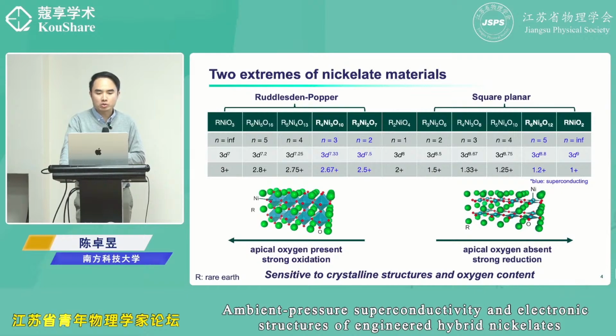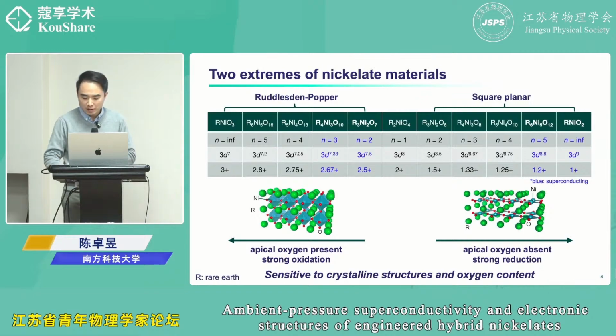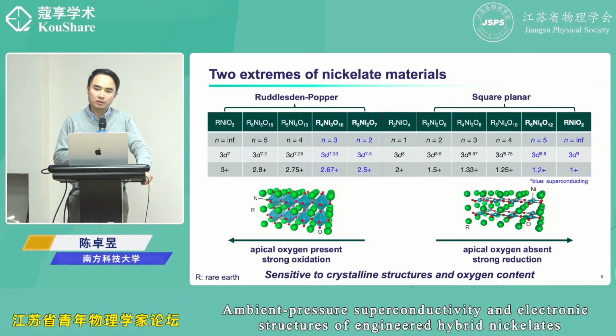And some are superconducting, some are not. So we also create this difficulty to differentiate which type is superconducting or which type is not. And so it's a difficult material in many aspects. Yeah. When you make the sample, you control the ratio between the R and the nickel. Or you control the growing parameter. All of these aspects, you need to control them perfectly. So this is why it's so difficult, and people are discovering this so late.